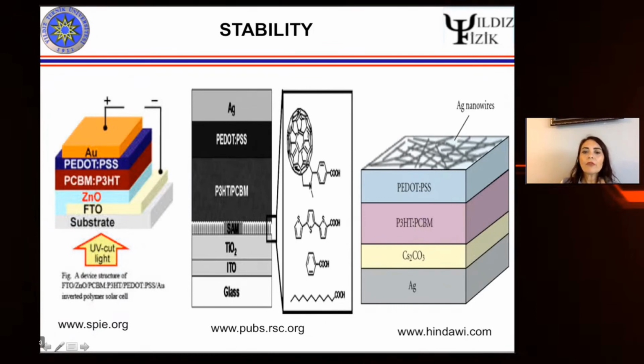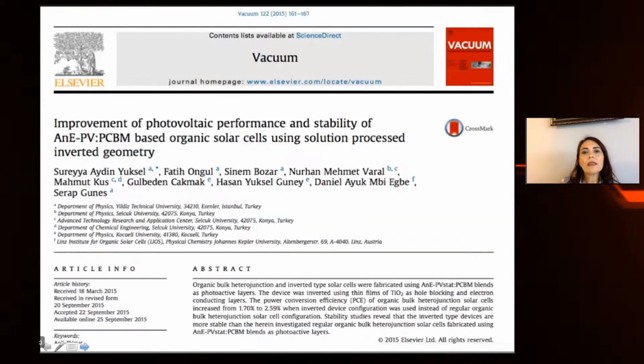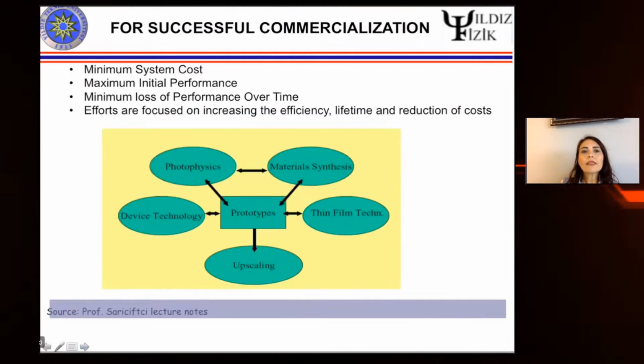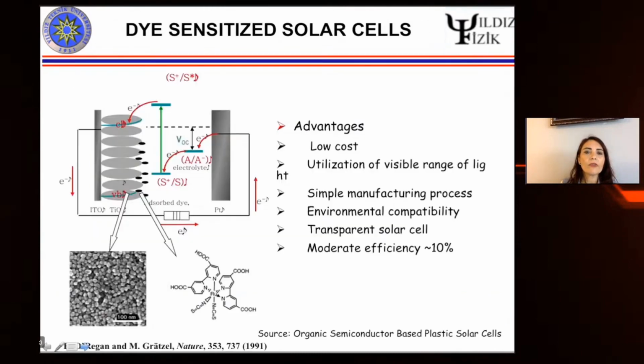So if we invert the device structure, this will enable us to use silver or gold electrodes. We also did a study and published it in the journal Vacuum, and we have shown that the stability was really improved as we invert the device geometry. For successful commercialization, we need the minimum system cost, maximum initial performance, and minimum loss of performance over time, and the efforts are focused on increasing the efficiency and lifetime and reducing the costs.